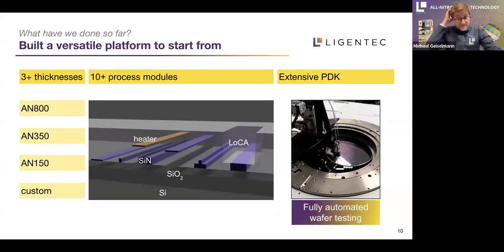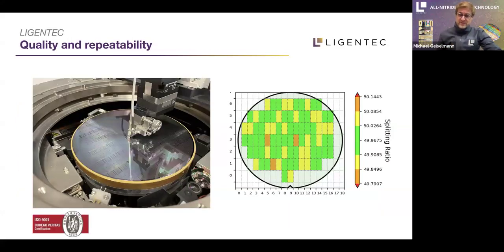It goes without saying that the software is only one part and simulation is only one part. You also need to test the PDK components. So all the building blocks that I just mentioned, they're tested within a wafer, from wafer to wafer, and from batch to batch, and like that we build statistics of the process, but also of the different building blocks. So if you put one building block in your circuit, we have extensive measurement data and statistics so that you can be assured that this building block works like predicted in the design manual. And this is one example for it.